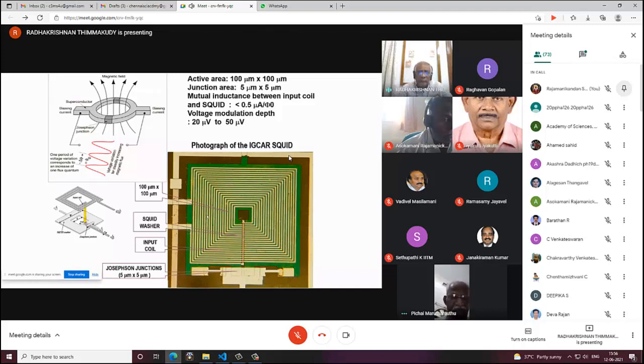It is a SQUID which is 1 millimeter in total area. The active area of the SQUID that couples to magnetic flux is 100 micron by 100 micron. These are superconducting junctions, 2 junctions of 5 micron by 5 micron. The mutual inductance between input coil and SQUID is 0.5 microampere per phi naught, and the voltage modulation depth is 20 microvolt to 50 microvolt. So this is the SQUID, and this is the magnetic flux modulation of current or voltage.